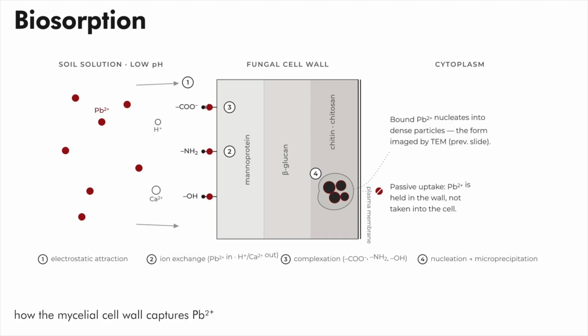What's going on here is a process called biosorption, and those lead particles are firstly getting attracted to the outside of the cell wall of the mycelium by cation attractions. That is pulling it through that first layer, the mannoprotein that you see there. It's very permeable, going through the beta-glucan layer, which is a little less permeable, more like a screen. And then it gets lodged in that last layer, which is mostly chitin-rich material, and it doesn't make it all the way into the mycelium, so the fungus is protecting itself by not having that go into the actual nutrient pathway, but it's getting lodged in that cell wall, and that's creating this polymeric encapsulation. So this is biosorption, basically pulling it in and locking it away.